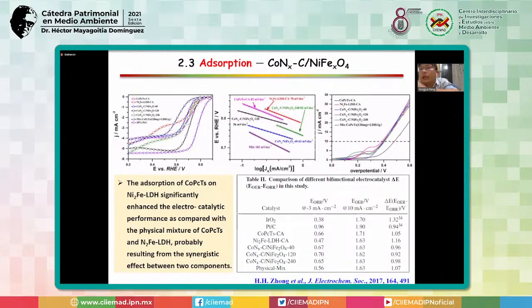So we can see here we just show absorption of CoPcTs on the Ni3Fe-LDH, so we can significantly enhance electrocatalytic performance as compared with the physical mixture of CoPcTs and the Ni3Fe-LDH. So that means between the components, we can get some synergistic effect between the two components. So that is why we put them together.